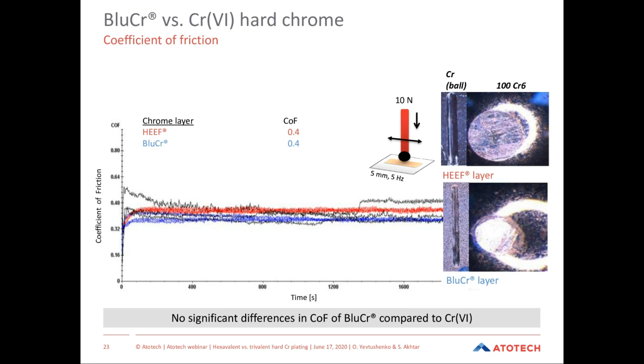Coming to the next point, which is friction, the coefficient of friction. At this point, I have to admit that there are several methods of determination of coefficients of friction. That's why, if you compare the data, you need to be sure that you compare data which were produced by the same measurement machine and method, especially method. Here the method is pin on disk. The sliding wear of the deposit is determined against a moving ball, the so-called counterbody. This counterbody can be made from different materials, and in this case, for this test result, it was hardened steel.